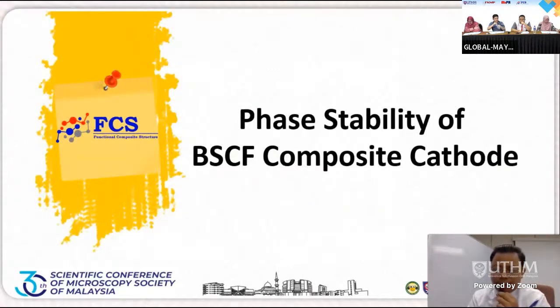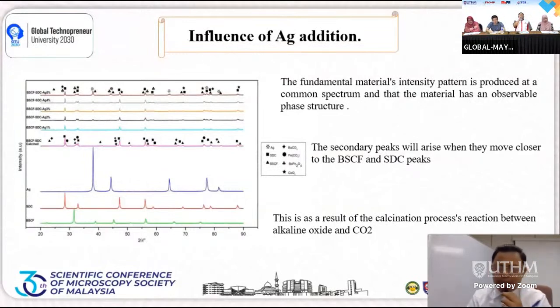Then I move on to the phase stability of the BSCF composite cathode. First, the influence of the Ag, argentum or silver, addition. As you can see in the figures, the Ag was added from around 1% to 5%, and there is also a sample without Ag addition, and the fundamental material intensity pattern was produced with this phase structure. As you can see in the diagram, the secondary peak arises when they move closer to the BSCF and SDC peak. This is a result of a carbonation reaction between alkaline oxide and carbon dioxide.